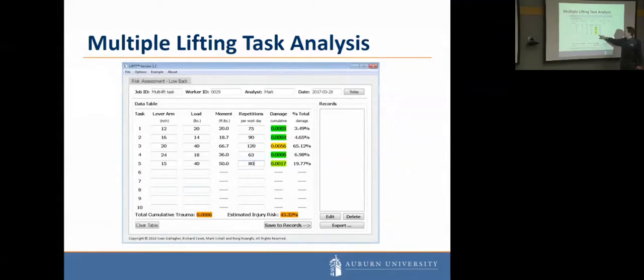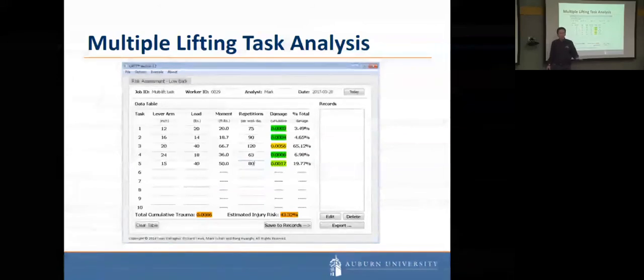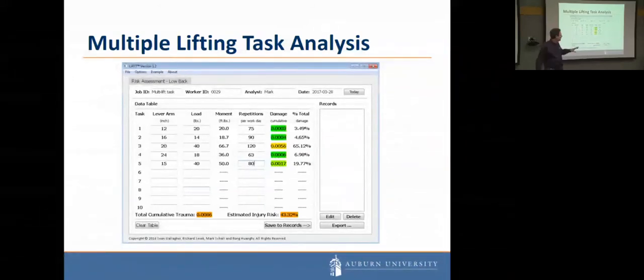And this other one here is about 20%. And the others are actually pretty small. Those are pretty reasonable. But this allows you to look at tasks and look at the cumulative load. We've evaluated this against epidemiological databases, and we would say that the estimated risk associated with this job would be about 43%. We're giving it an orange rating, orangish. We color map this.